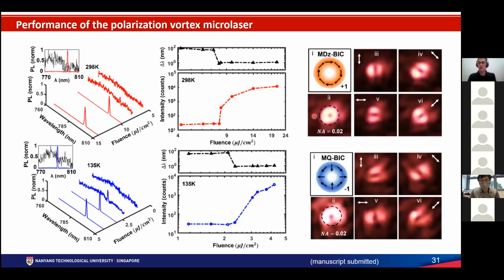When we do real space imaging of the device, of the emitted light, we observe a typical donut shape, so the typical vortex shape that we expect. And then we follow the winding of the polarization by rotating a polarizer in front of the camera. You can see that for the mode that is a magnetic dipole, the winding number is +1. And for the magnetic quadrupole, you can see that the winding is in the opposite direction, giving a topological charge of -1.